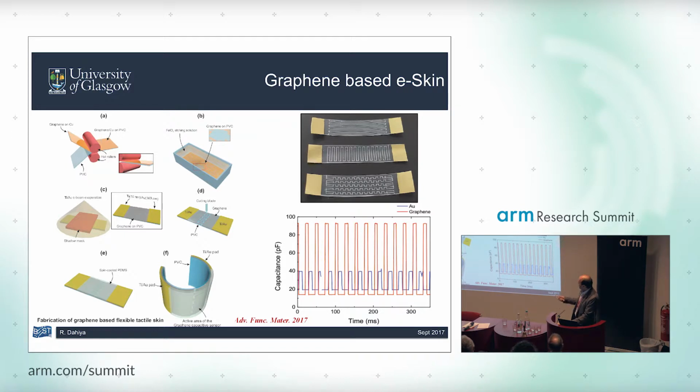And now after that, we do not use lithography, because lithography is known to damage graphene. So what we did, we simply used a blade cutting tool. Yes, this is about 30 micrometer. There are other tools available. So that's how we got it, and the performance we got in terms of sensors was much higher than similar sensors obtained with other metals such as gold.